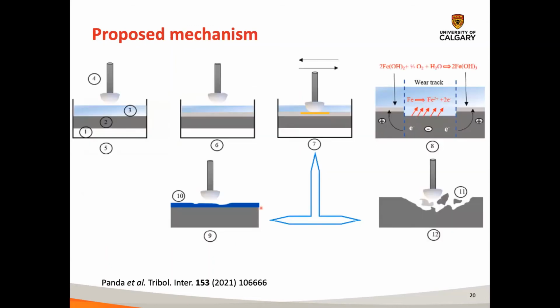So the idea, or our proposed mechanism, is that when we put the steel, this is the counter surface, the electrolyte, the steel, and the stage that's moving back and forth. When we put this in with the steel and the electrolyte, we form a rust or a scale on top of the steel, and then we rub the counter surface back and forth, and we basically tear off the coating. We form wear particles, which are hard, and then this in turn starts removing more and more material. We also have corrosion happening of the steel at the same time.